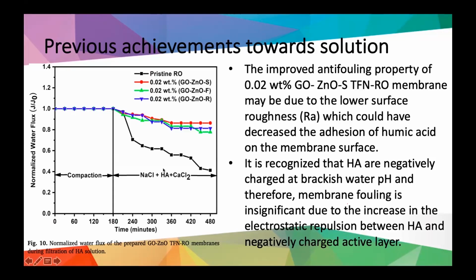The same fouling solution shows that the pristine membrane has a high decline in the normalized water flux, normalized between the instantaneous flux and the flux at the beginning. It decreases dramatically from 1 to around 0.4, which is a great decline in the flux. This means the membrane loses more than 60% of its activity to produce permeate water.